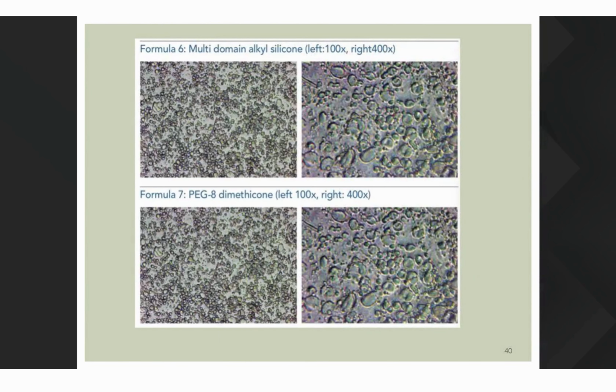And then finally, when we start doing things with multi-domain, one of the interesting things about multi-domain is there's a solid in there. So what happens when you put the solid domain material in, you heat up the product to make the emulsion. Well, everything's liquid at that point, and this particular alkyl silicone stays in the oil phase, and as it starts to cool down, you start to generate some structure to the oil. Now, viscosity of the oil phase, as it goes up, improves emulsion stability. So this is a way to actually improve your emulsion stability in addition to changing the rheology. When you go back and look at the PEG 8 dimethicone, you can see it also changes. So those two are very different than the other ones. So we're doing things that affect emulsion stability now, which is a very desirable thing in many areas.